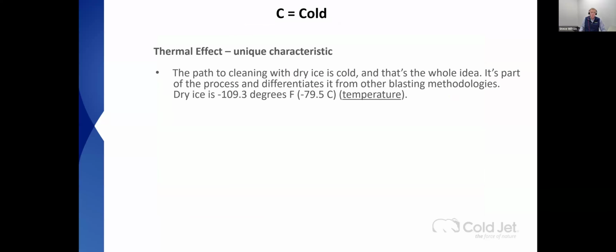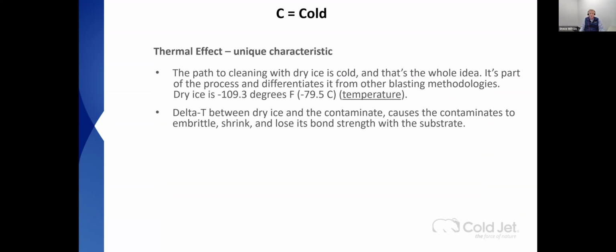You got the impact, we move to the cold, so the path to cleaning with dry ice is cold. That's the whole idea of it. It's what separates us from other blasting methodologies. It's minus 109 degrees. That delta T between the dry ice and the contaminant causes the contaminant to brittle. It shrinks, loses its bond strength with the substrate.